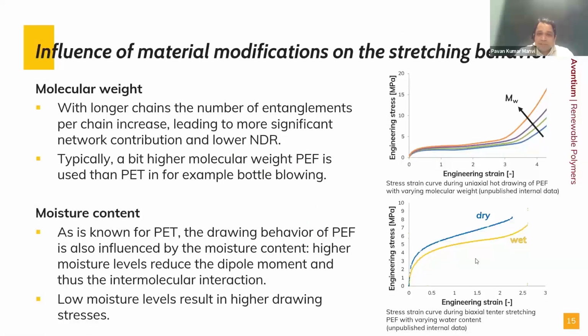There is again some more data which is important, because when we talk about polymer behavior, it is very much dependent on the molecular weight. Higher molecular weight means the entanglement per chain will increase, and therefore the natural draw ratio will be lower. There is another study where we realized that to get similar melt flow behavior, the PEF has to have a higher molecular weight than PET. The impact of the molecular weight on the natural draw ratio is shown in the right side curve. Additionally, we have also studied that the moisture content can impact the stress strain behavior, because water molecules from the moisture have a plasticizing effect on the PEF, and therefore this effect also needs to be considered during processing. And plasticizing effect means higher strain under the same loading.